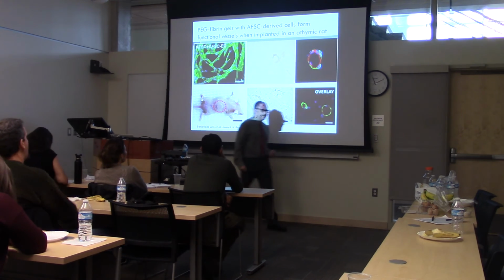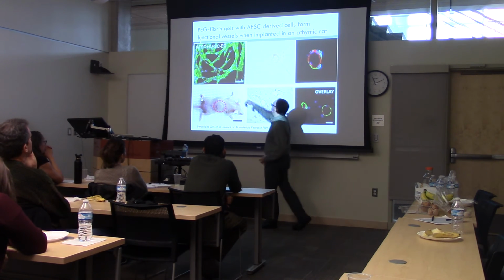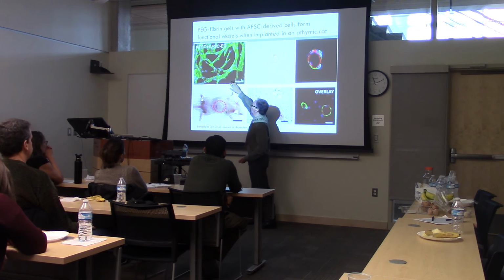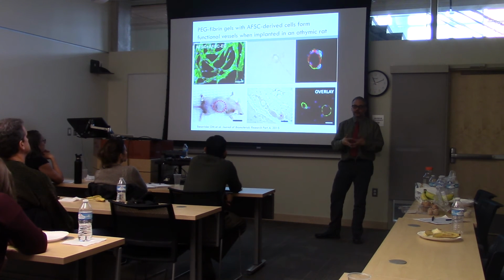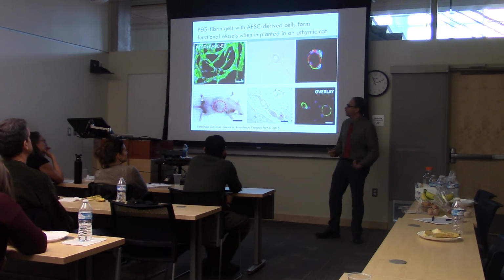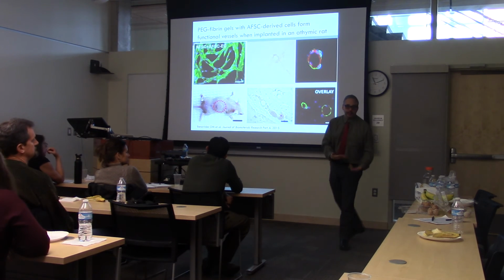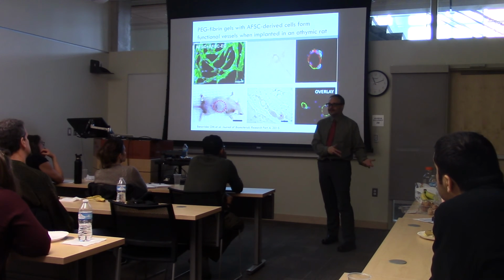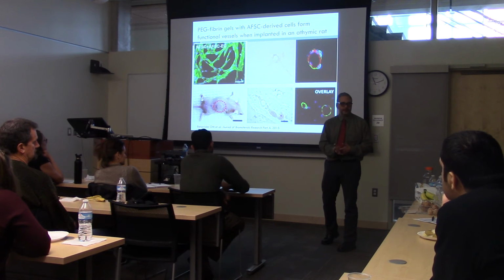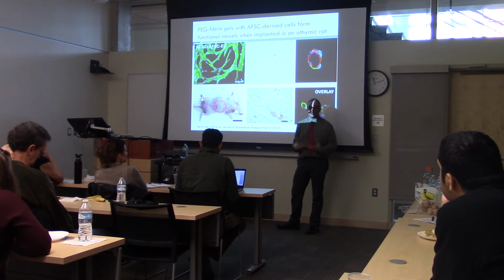Perfect. So we can put that in, and I can show you these top slides are in vitro, and all of this is published, but I can answer your questions about it too. You put it in, you form these capillary-like networks. If it's just endothelial cells, you form capillary-like networks in a week, and then they fall apart by 2 weeks. We found out if you add in a 4-to-1 ratio just unfractionated amniotic fluid stem cells, so these are stem cells, they act like mesenchymal stem cells, and they can turn into these smooth muscle-like or pericyte-like cells that can surround blood vessels, and it seems to stabilize the blood vessels. So if you add those, then you get blood vessels that after 2 weeks are stable.